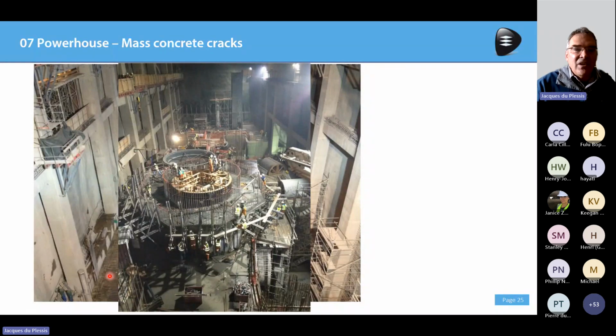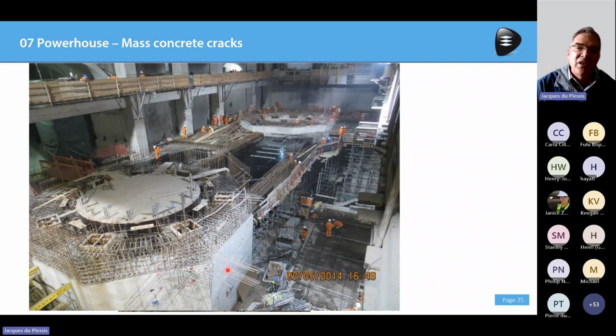And on this draft tube concrete encasement, we got temperature cracks in the concrete. So the rule of thumb is, when the concrete on the surface takes on the ambient temperature, say 20 degrees, and the concrete in the middle is more than 20 degrees warmer than the concrete on the surface, so more than 40 degrees with the hydration temperature, there's potential for the concrete cracking.